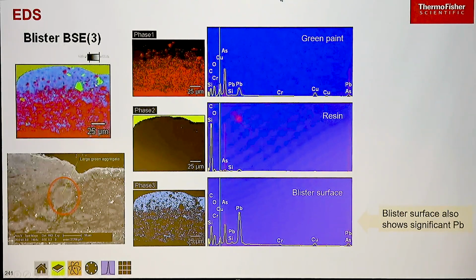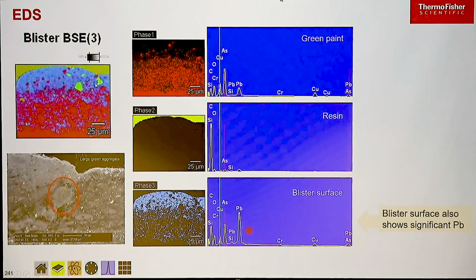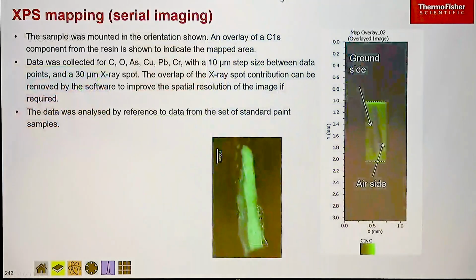So the green paint here, looking at the blister feature, we can see on the surface of the blister lots of lead again, and arsenic in the green paint that's underneath it. So again, at the surface where we're seeing those little particles, and on the surface of this blister feature, we're seeing lots of lead. So that's giving us an indication that might be something to do with what we're seeing.